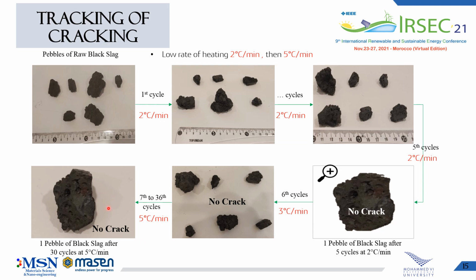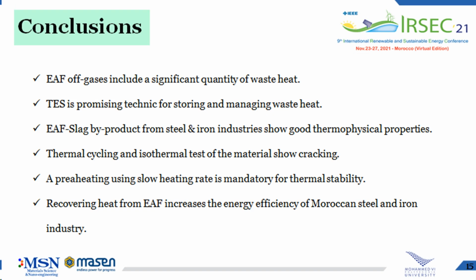no cracking was detected. Thermal energy storage is a promising technique for the recovery of a huge quantity of waste heat generated by industries during their activity. And the electric arc furnace slag byproduct presents a good thermophysical property. Even if the material shows some cracking behavior during the thermal cycling and the isothermal test, the only thing we recommend is slow heating rate during the first few cycles to ensure thermal stability of the material.